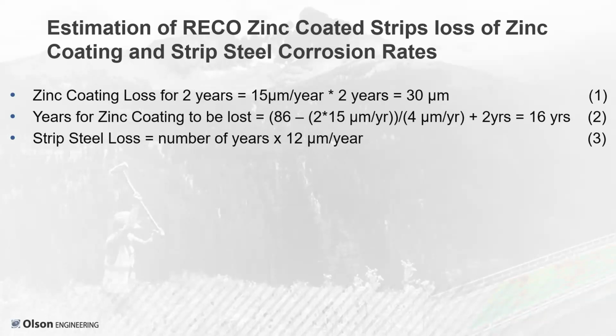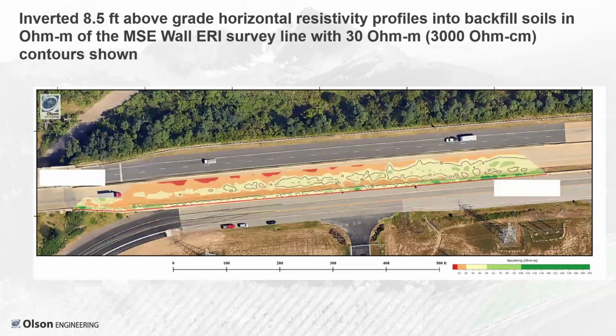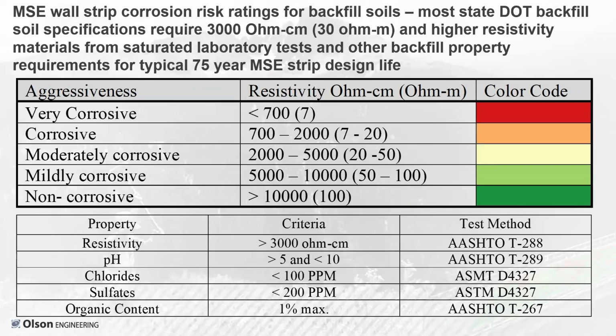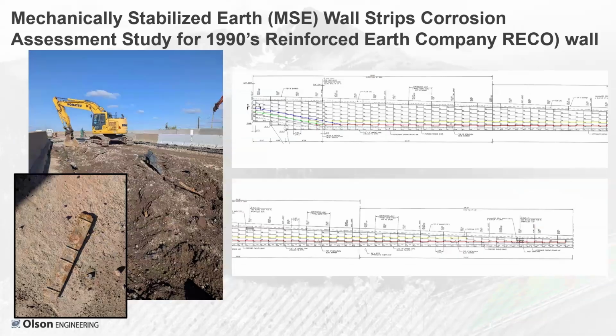Okay, thank you, Jared. This was our second project. We'd earlier looked at 7 walls with similar resistivity methods to predict remaining service life. One thing I'll mention and back up just a bit as a preface to this, that when they first discovered that they had some concerns about the corrosion of the zinc-coated galvanized strips, which were the standard strips, non-lead, 50 millimeters by 4 millimeters with a zinc coating. And as in any wall, the deeper down you are, the longer the strips go back into it. But this was right at the top, and here they've found the corrosion.